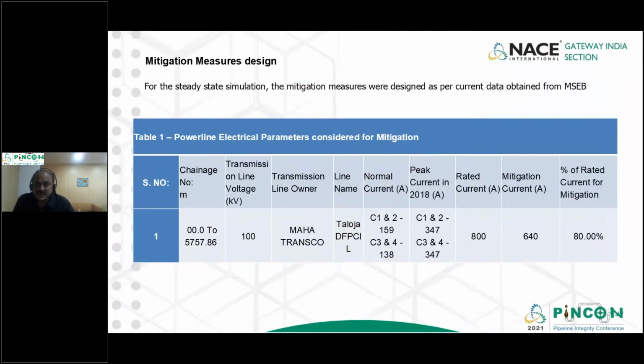So for a steady state simulation, the mitigation measures were designed as per the current data obtained from MSEB. Between chainage 0 to 5757, the line voltage was 100 kV, and this is the Maharashtra Transco, MSEDCL line at Taloja. The peak current we found in 2018, the rated current, the mitigation current, and the percentage of rated current for mitigation was 80%.